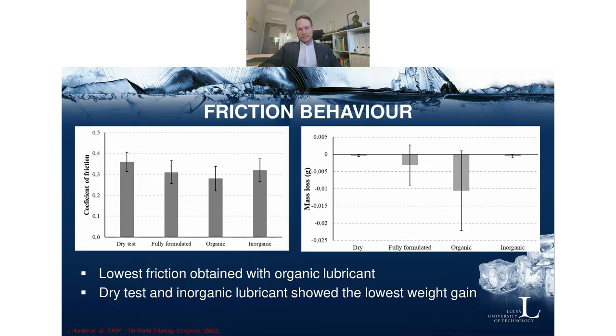To the right, you see the mass loss. And this is obviously now a negative mass loss, which implies that we have a material transfer taking place, plus some residual lubricant that is still there on the surface. What you can notice here is that the inorganic lubricant shows very little material transfer, whereas the organic one shows quite significant material transfer, and the fully formulated is somewhere in between. So increasing the concentration of the inorganic part of the lubricant improves the performance relative to the other lubricant, although the dry test shows very little material transfer as well. So this is kind of a status quo in a way, changing to this lubricant.